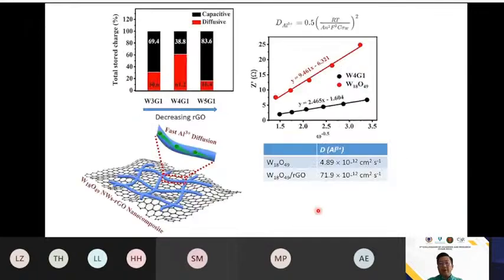So what is the role of the graphene in this case? Why does it contribute to the higher charge storage? We can find it because, as I mentioned, this is due to the diffusive nature of the aluminum ion. It can diffuse faster, it can store higher charge. We run through the test to check on the diffusion coefficient of the aluminum ion within the crystal structure. And we show that with this graphene oxide added, the diffusion coefficient of this aluminum ion is increased up to about 14 or 15 times as compared to the tungsten oxide itself.